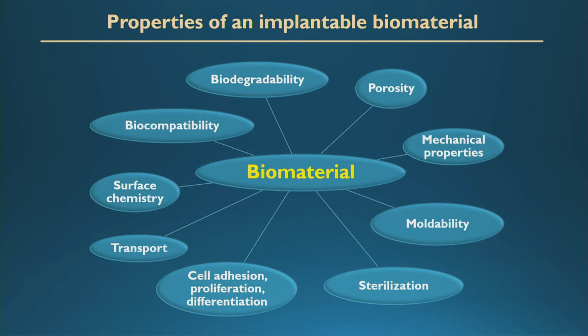As I mentioned, hydrogels have this moldability property that is very attractive for spinal cord injury. I also mentioned the mechanical properties should match those of the spinal cord, because we don't want it to collapse, or, if it's too stiff, to cause further injury. And the porosity is also important to allow extension of the axons and regeneration of cells.